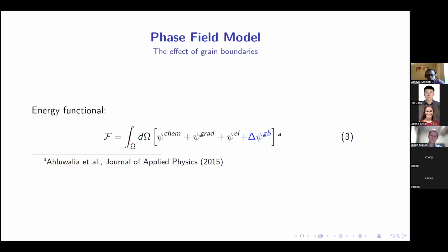Okay, so in order for us to model this using a phase field model, we establish a very simple phase field model of martensitic transformations. That model has been used by many researchers. It's actually quite simple, where the total energy density can be additively decomposed into a chemical part that is temperature dependent and tells you whether the austenite or the martensite is stable at that particular temperature.